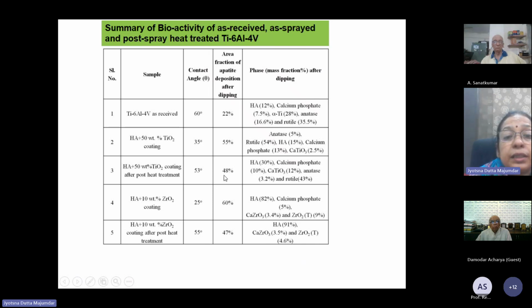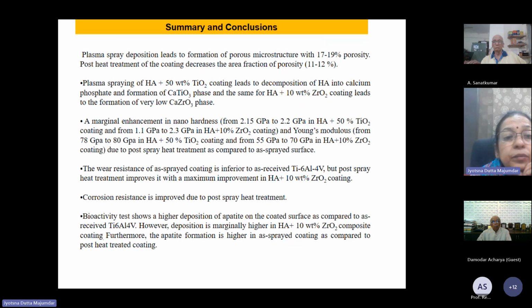So there is a little bit of reduction in the bioactivity, but these are all experimental results, and bioactivity is a crude way of measuring the bioperformance of the material. So we have to go for in vivo analysis to know how it is anchored to the tissue, hard bone actually.